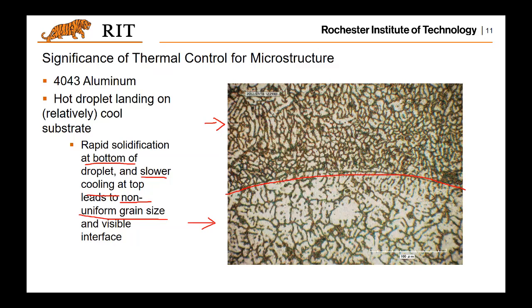So this kind of microstructure will lead to poor material properties, and that will essentially affect the usage of this kind of process for many applications, because there will be some weak points in the structure, and that could break the whole object in certain extreme cases. So that's why this kind of thermal control is important. Basically, you want to control to make sure the substrate temperature and the droplet temperature are not too different, and that will avoid such problems quite a bit.